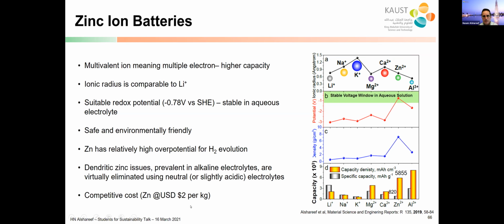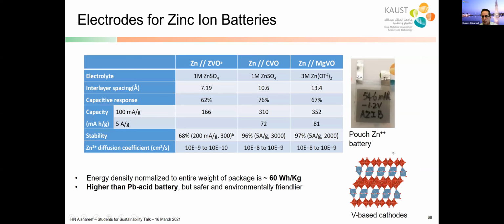So there's a price advantage, there's a safety advantage, there's an environmental friendliness advantage, but you have the issue that the voltage of the battery is kind of low because you are dealing with aqueous electrolyte. So we have been working on oxide cathodes. These are some of the batteries we are developing in our group, getting energy densities as high as 352. If you normalize density to the weight of the entire package of this battery, for example, we can get 60 watt-hour per kilogram. Actually, this competes with the lead-acid battery in a car, although the rate performance is still inferior. But in principle, if you can improve that, you can replace maybe one day the lead-acid battery.